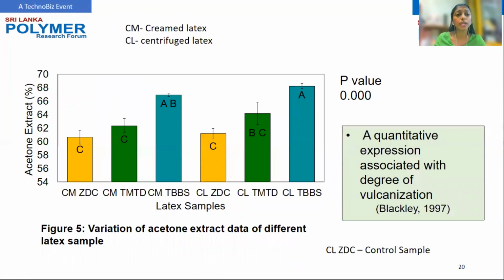Acetone extraction is a quantitative expression associated with the degree of vulcanization, as discussed by Blackley in 1997. As you can see in figure 5, acetone extraction values also follow the same trend observed for swelling index. It could be seen that the highest acetone extract value was exhibited in the TBBS system. This shows that in this system, curing agents incorporated may remain unreacted and be extracted with the acetone. This supported the earlier explanation given for the substantially low tensile and tear strength of TBBS systems.